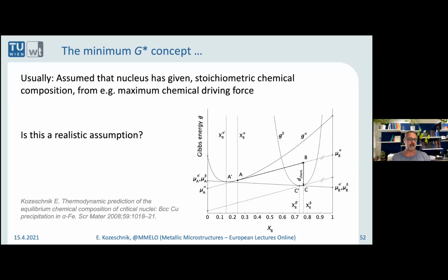Because the copper phase is actually a solution phase, it can contain more or less iron atoms also. In fact, it can span the entire compositional range from 100% iron to 100% copper. The problem that I encountered is here on the screen. When you have two phases in the Gibbs energy composition diagram, like this is the alpha matrix, and this would be the precipitate, and the precipitate has a certain range of chemical compositions where it exists, then you always need to calculate chemical driving forces.